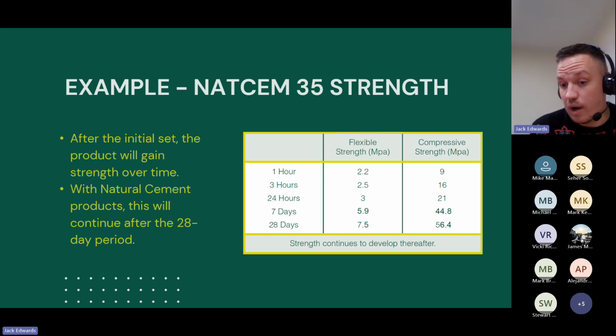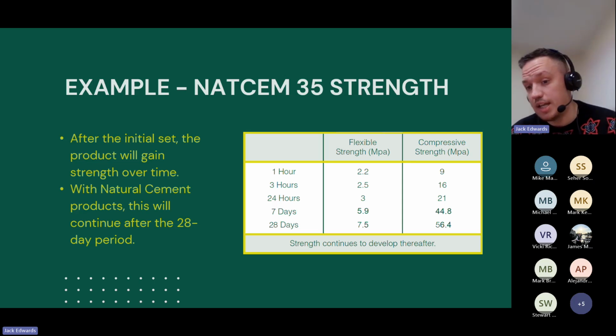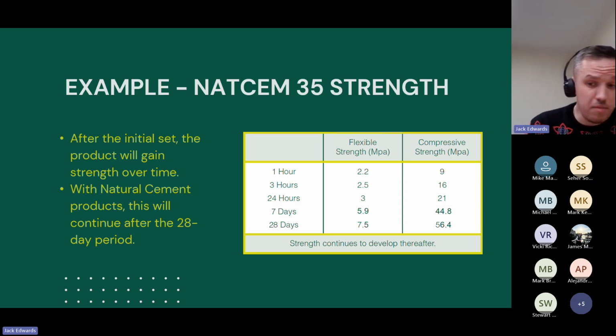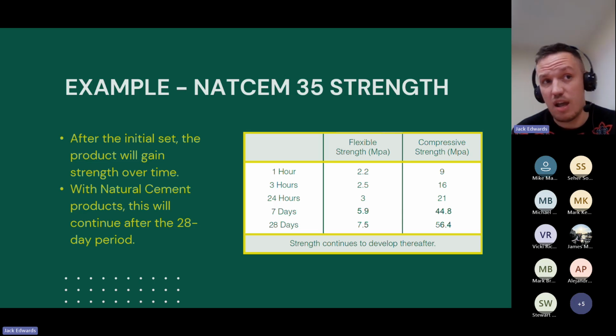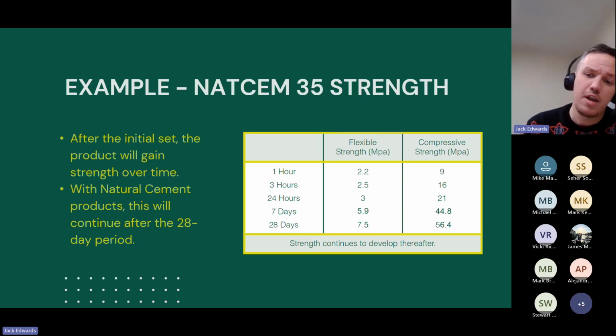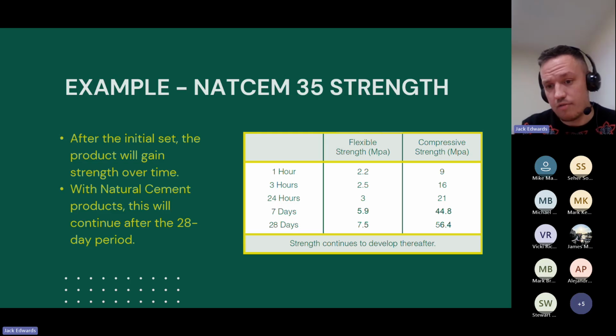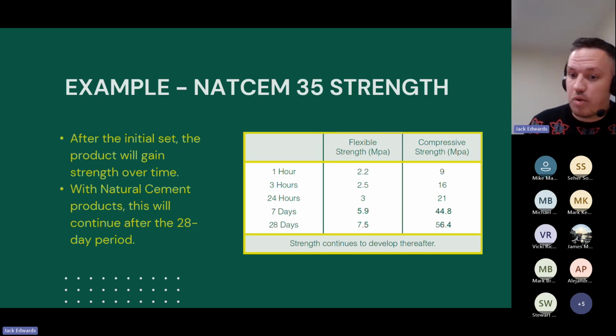the strength gain will be quite considerable. So you do get a certain degree of that with all cementitious products, but with a natural cement product, it is much more prevalent. So after 12 months, the strength gain will probably go up on average around 50% compared to what it was at 28 days. So even if you are working in cold temperatures and the strength gain is taking slightly longer in the first instance, the product will always meet the design requirement and always exceed it because it will continually gain strength, like I said, even after the 28-day period.